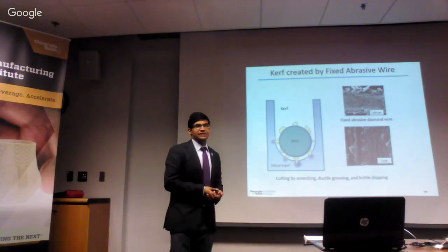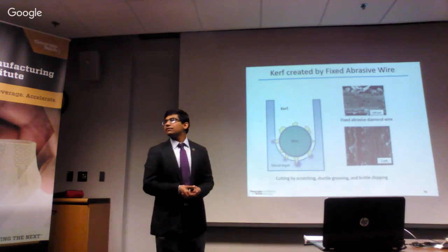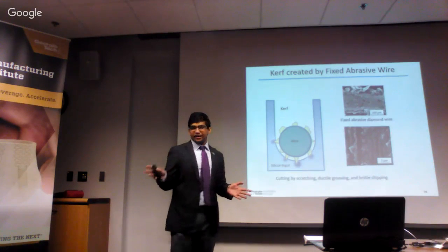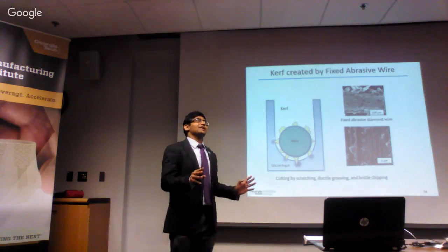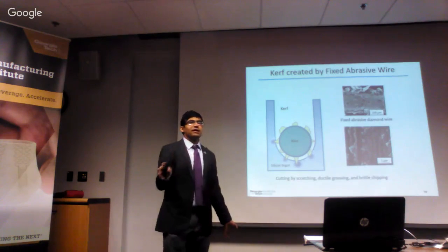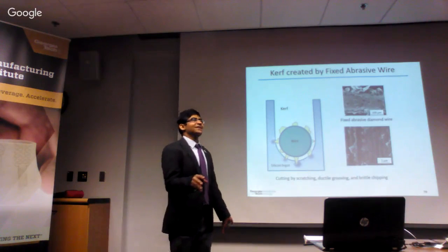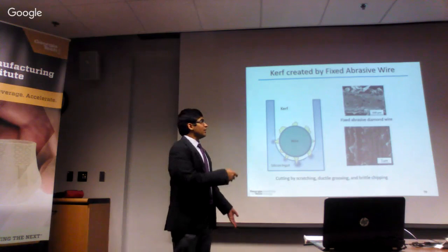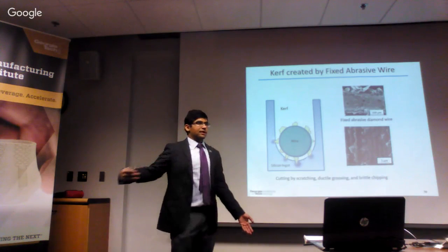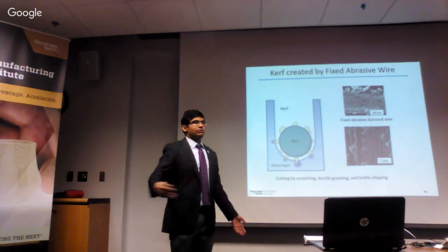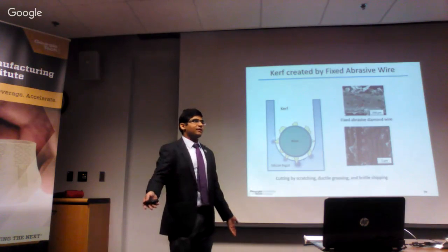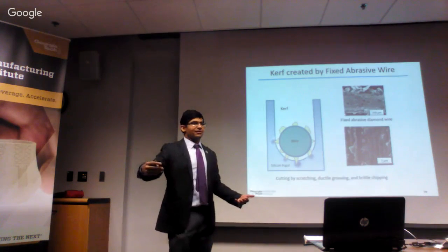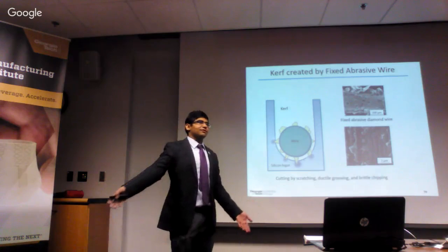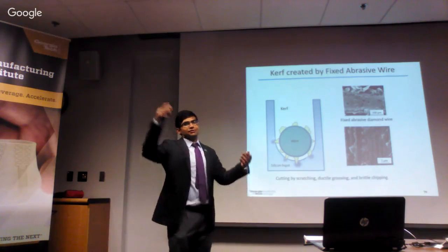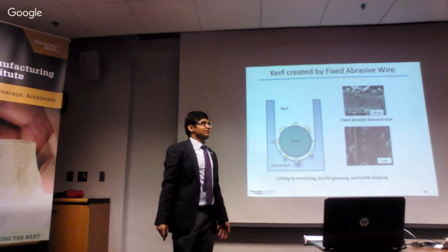But is there any guarantee that they remove all of the cracks? It's not guaranteed. So it's best to reduce cracking as much as possible. And cracking is a stochastic, random fracture process. So like I am investigating, let's say, 25 locations, and I found the maximum crack is 9 or 10 micron. But I might have missed a 40 micron crack, which is there. And that could cause fracture later on.